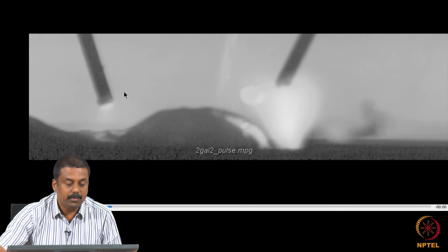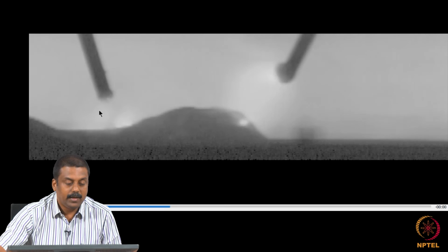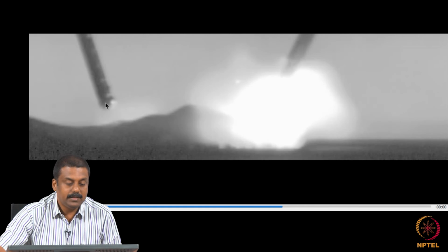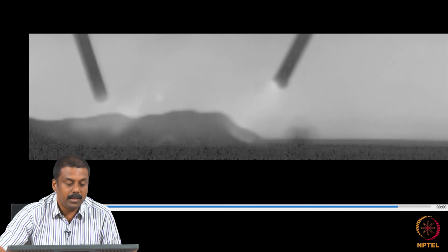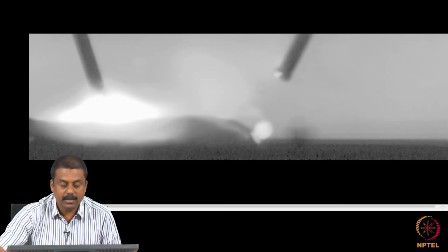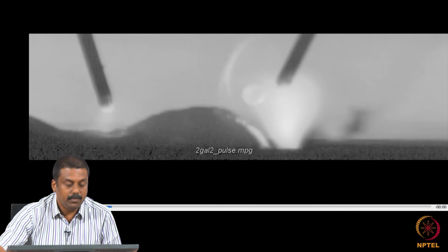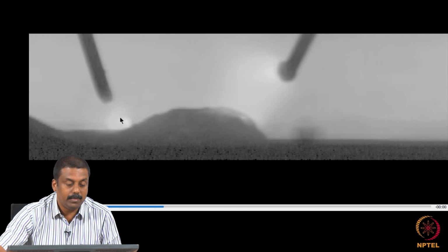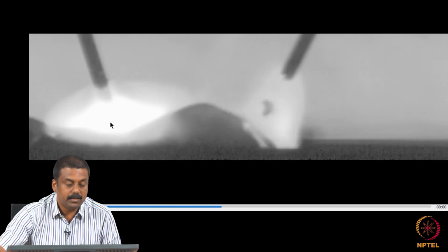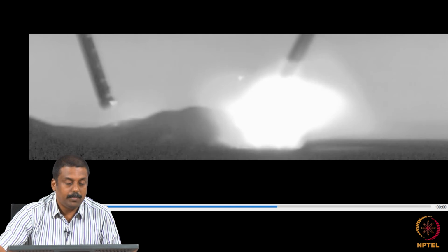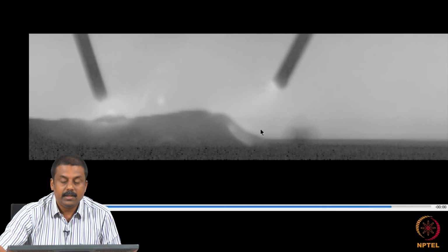And in this case, because we do not maintain the current higher than mean current as in a conventional GMAW process, we increase the current only during the pulsing period, and then during the background period we maintain a very small background arc, as you may see in this video. Because of the use of both the pulse current and the background current, we have a more stable process where we detach one droplet per pulse, and by changing the frequency of the pulsing we may also change the droplet transfer frequency.